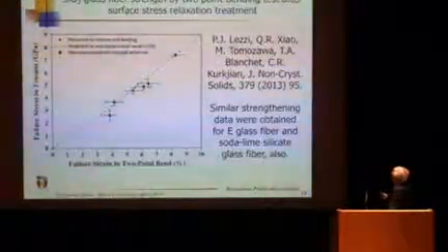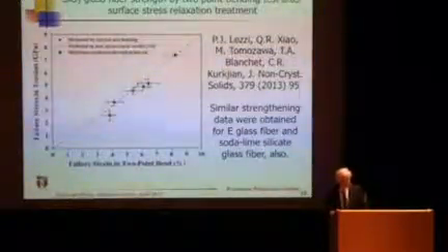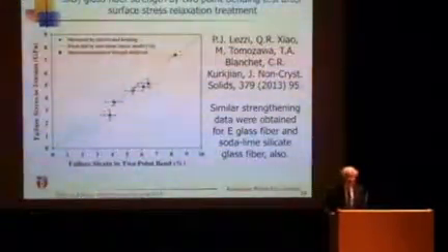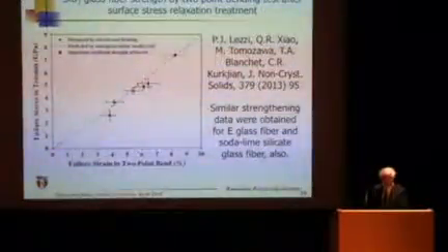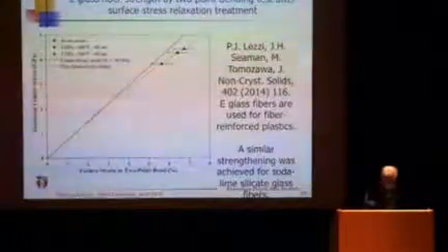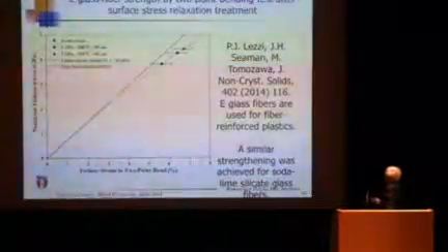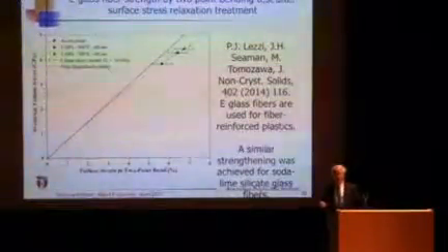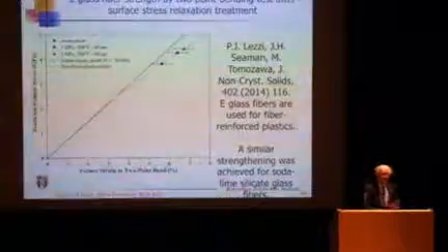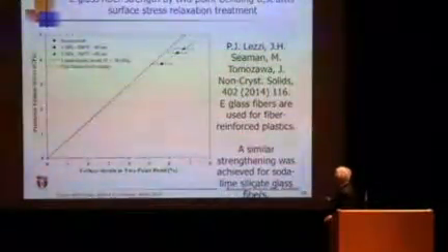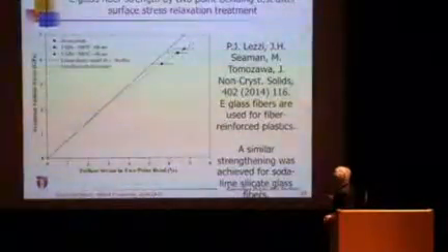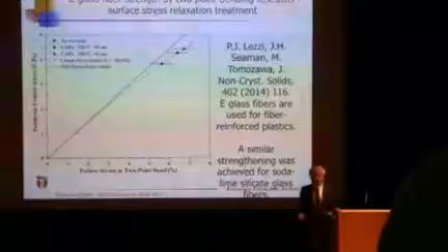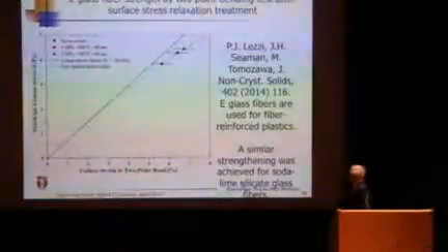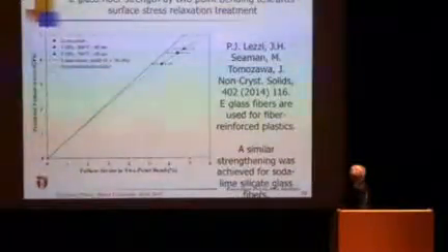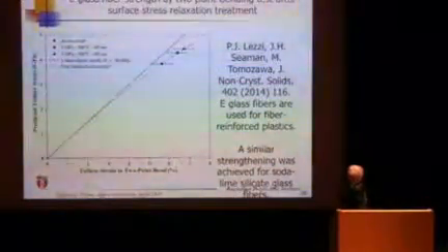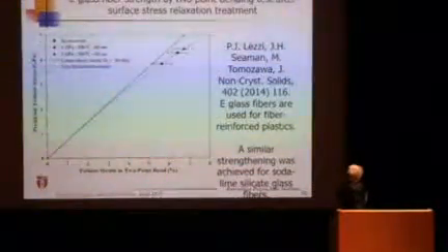By the way, this first author, Peter Lezzi, because of this work, received the Cridle Award given to the best graduate research done last year. And he continued to apply it to E-glass fiber. E-glass fiber is used for fiber reinforced composite material to make a stronger material. And some high-end composites are trying to replace E-glass fiber with graphite or carbon fibers. I'm hoping that this method of strengthening, but this is the original E-glass fiber, after simple treatment, 1 gigapascal tensile stress, 200 degrees, 60 seconds, we can make this stronger.